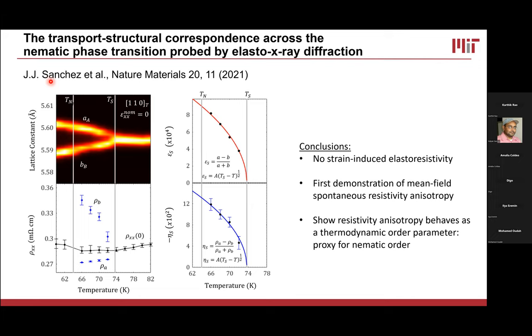If I do this at different temperatures, I can get a plot that shows the smooth splitting of the two lattice constants when I hit the nematic transition, and also the smooth splitting of the resistivities when I hit the nematic transition. Then I can look at the normalized anisotropies of the two. So I see an orthorhombicity that smoothly increases at the nematic transition, and also a resistivity anisotropy that smoothly increases. And they have the same mean field ordering behavior. They fit to the same line, essentially, with only a shifted magnitude. So what this shows us for the first time is that there is a very clear mean field behavior of the spontaneous resistivity anisotropy. And that shows that the resistivity anisotropy behaves like a thermodynamic order parameter. That means it behaves like a proxy for the nematic order.